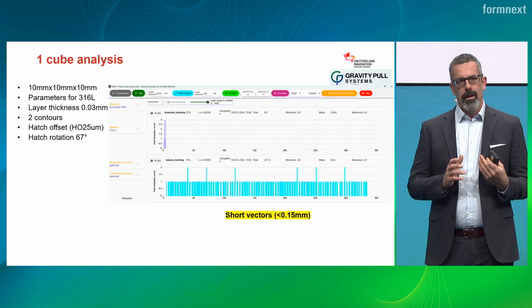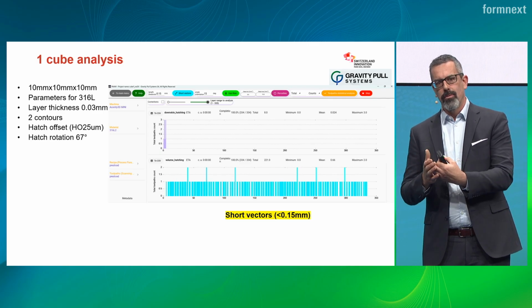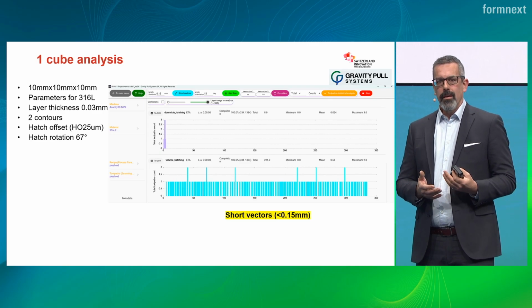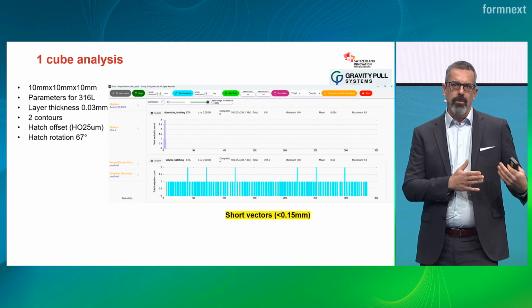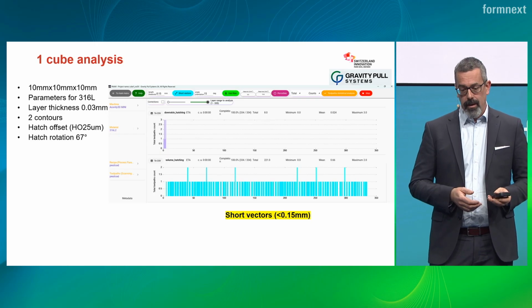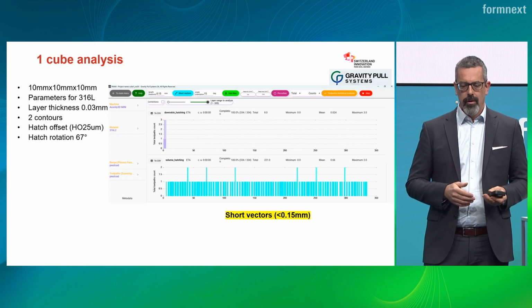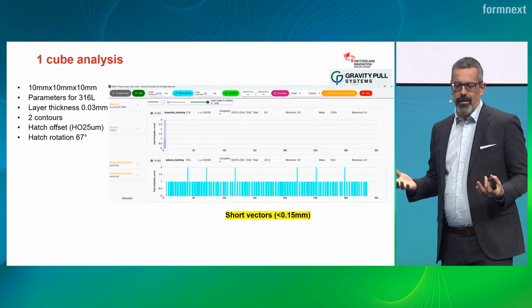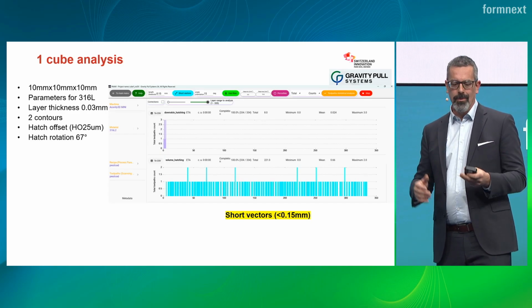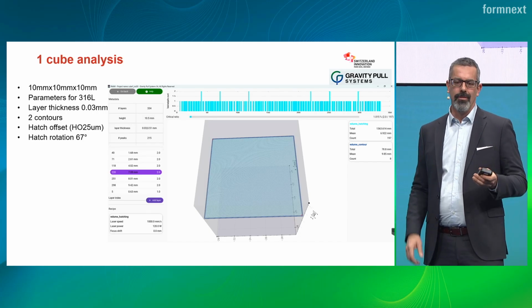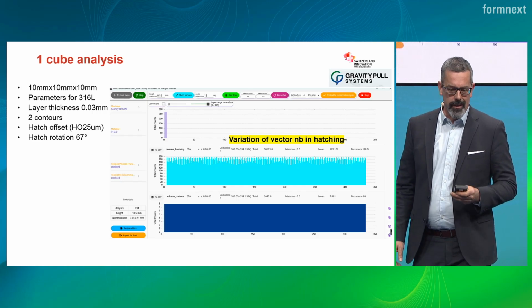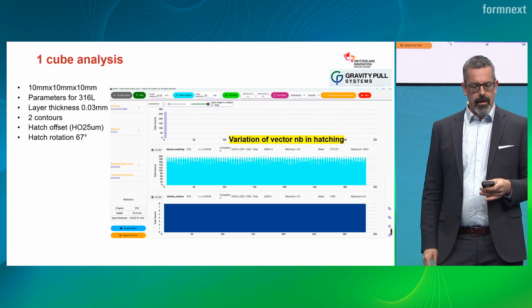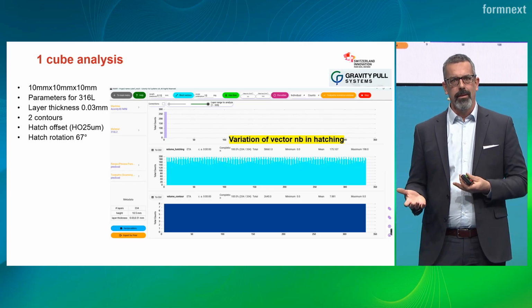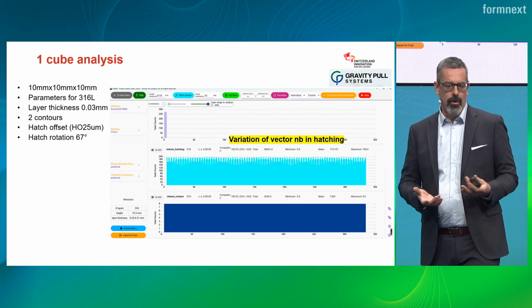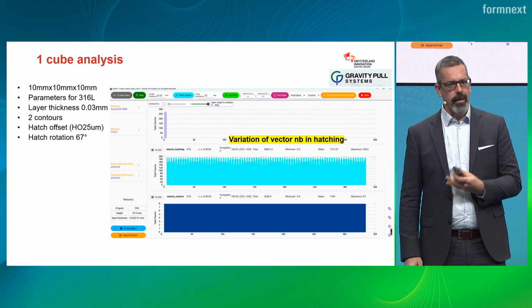Another parameter is the short vectors. During short vectors, the laser might have problems to reach a speed, so you try to filter out those. You detect here vectors that are shorter than 150 microns, and you see already in the cube between layers you have this in the blue one. As you might expect, there is either 0, 1, or 2, and not surprisingly, they are found in the corners of your cube. So very simple and very understandable. Already here, we see that there is a variation in number of vectors per layer. It's no surprise, but it's notable that already in the cube you have different number of vectors per layer.